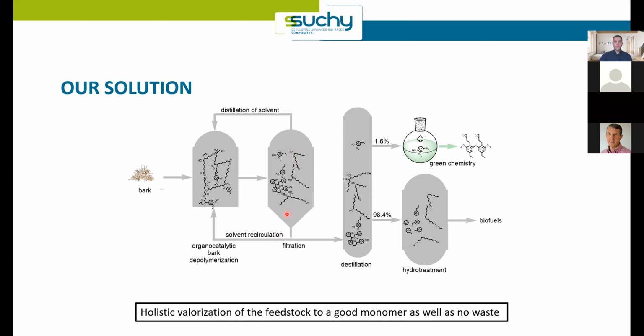And then the oil that is generated was transferred to a distillation tower, and 1.6% goes to this ethyl glycol that we could then apply green chemistry to produce this diepoxy bis glycol monomer for polymers. And the rest we could hydroprocess to generate biofuels. So in this way, we don't get any chemical waste. Everything goes into high value applications.